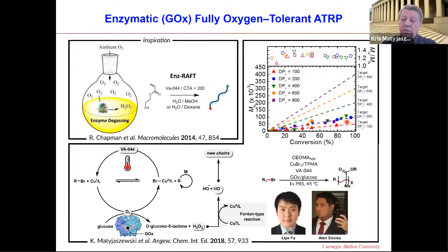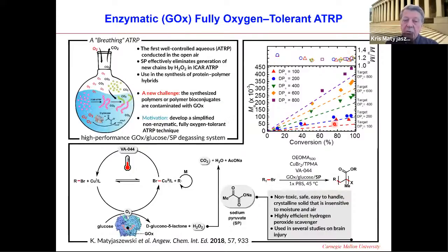How can we avoid formation of these new chains? Because if you want to make conjugate block copolymers, as Craig said, or star polymers, or any other materials grafting from surfaces, we should avoid these spontaneously formed chains. So we were thinking about it, and Alan and Liye Fu came with an idea borrowed from biochemistry, from Krebs' respiration cycle, that one can use pyruvate. Sodium pyruvate will react with hydrogen peroxide very, very fast, faster than the copper species, and produce inert carbon dioxide, water, and the corresponding acetate anions. So more or less, it is a very simple process. It's a non-toxic, safe system, highly efficient for hydrogen peroxide scavenging.